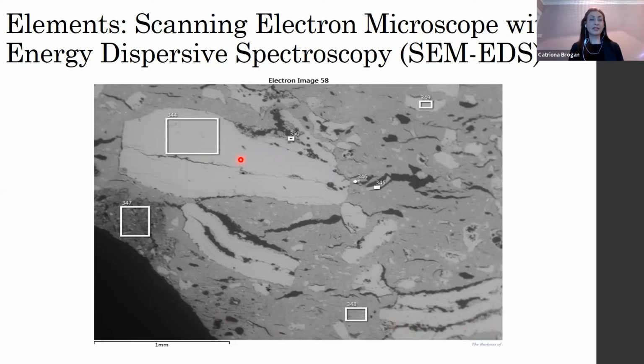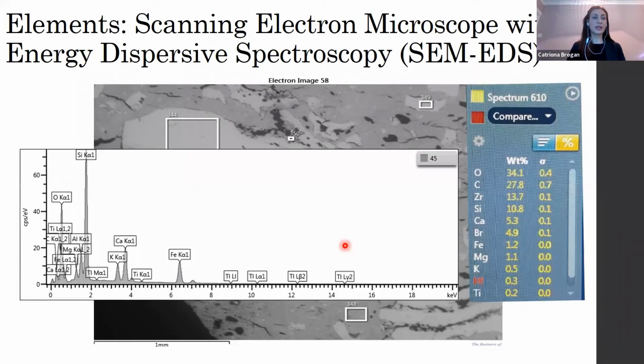and that was representative of the makeup of the sherd as a whole, and then this allowed us to compare these general areas to each other, so that we could form an idea of different fabric groups. The sort of readout that you get with the EDS basically gives you a spectrum, and then you have a series of peaks that occur along it, and it will tell you which elements they are. So silicon, calcium, titanium, iron, etc. And then it gives you a weight percent. So this just gives you quite a detailed understanding of what elements are present and in what quantities.